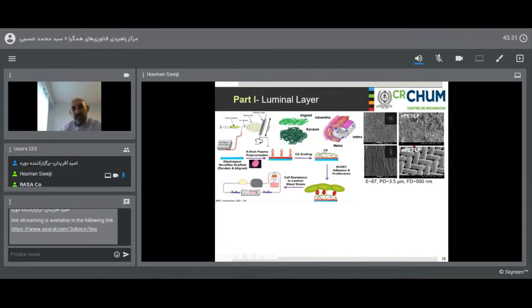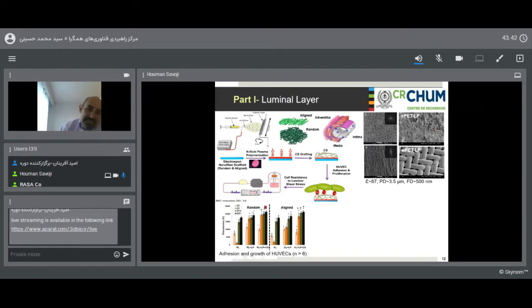So you should have a monolayer of endothelial cells. The pore size of our fibers is really small, so the endothelial cells cannot infiltrate inside the structure. So this is really suitable for our application. And then once we see the endothelial cells, we study the adhesion of the cells.